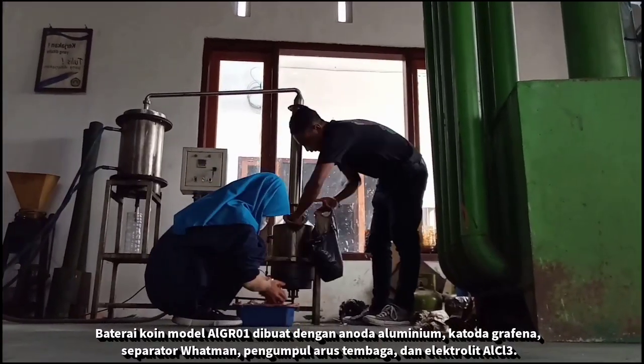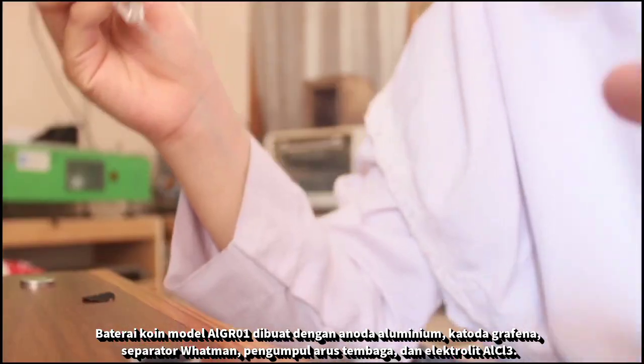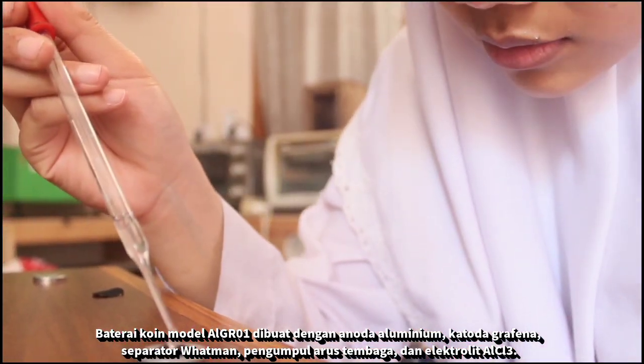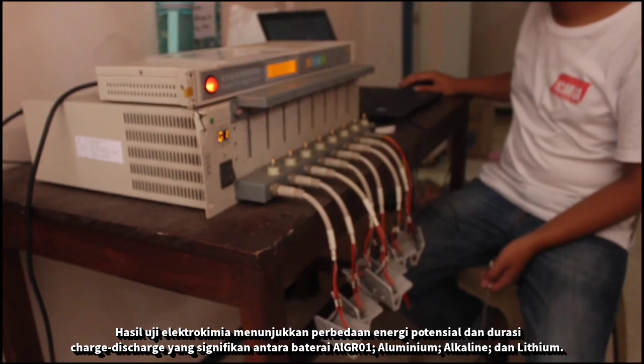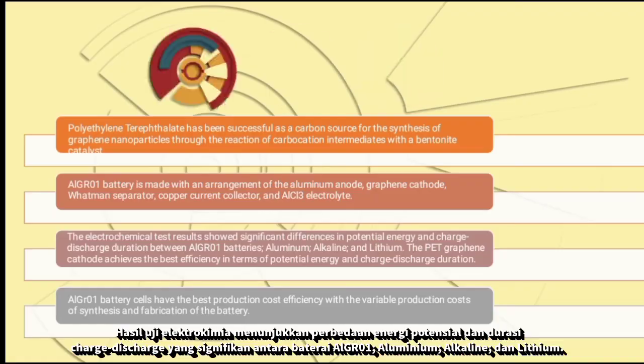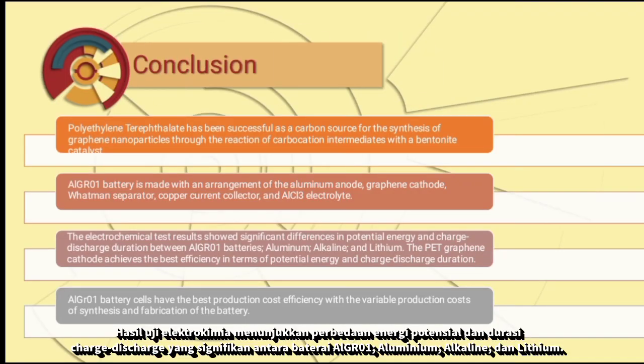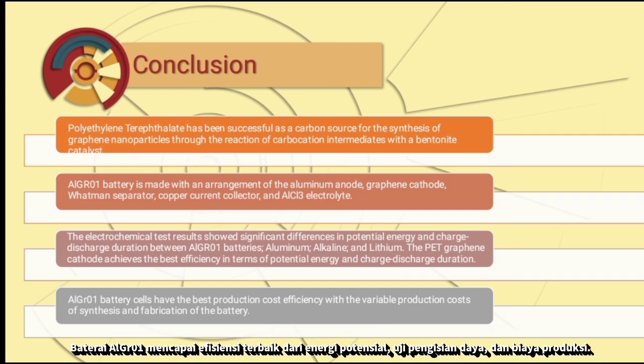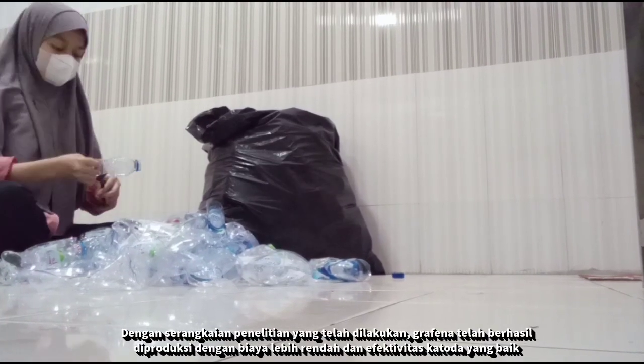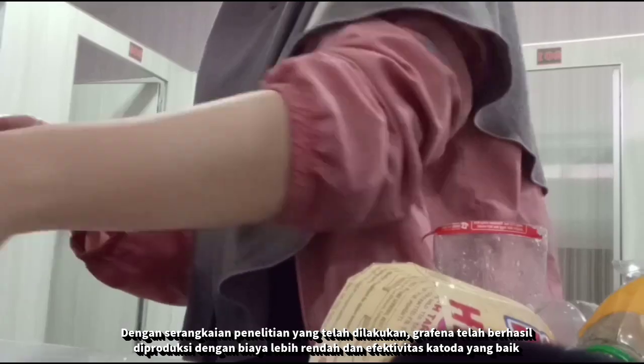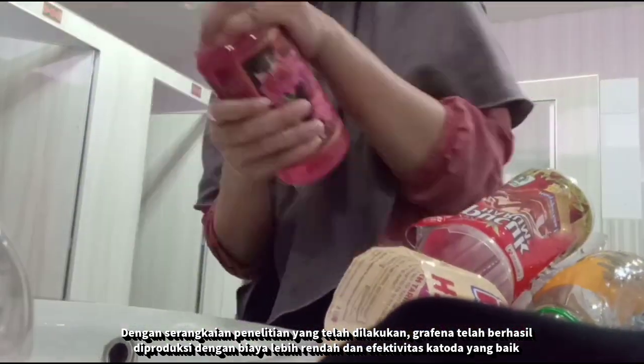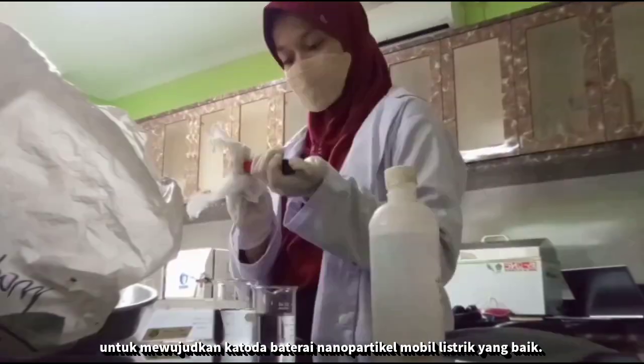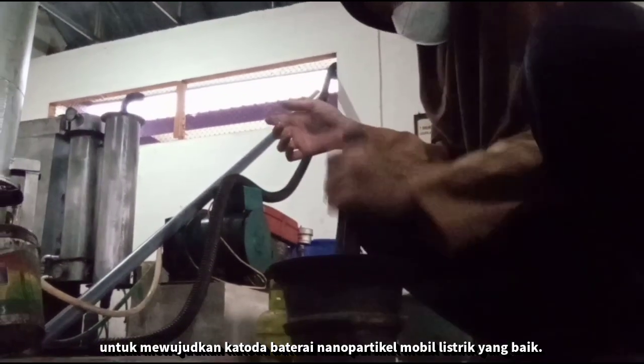The coin battery is constructed with an aluminum anode, graphene cathode, separator, copper current collector, and aluminum chloride electrolyte. The electrochemical test results show significant differences in potential energy and capacity between AlGR01 batteries, aluminum, alkaline, and lithium. The AlGR01 battery achieved the best efficiency in terms of potential energy, charge duration, and production cost. With a series of studies that have been carried out, graphene has been successfully produced at lower cost and with good cathode effectiveness to create good cathode electric car nanoparticle batteries.